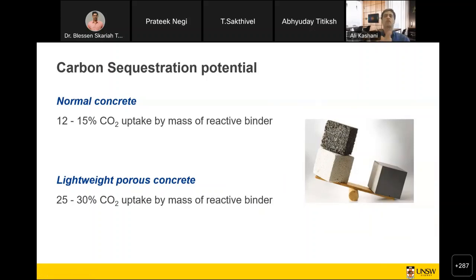So for normal concrete, if the process is right, maybe you can get 12 to 15% CO2 uptake per mass of the reactive binder, mainly cement and other binders. But if you use it in lightweight porous concrete as we've done, that can double the amount of CO2 sequestration.